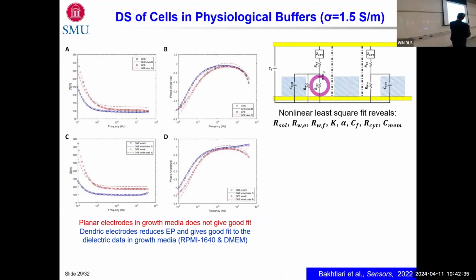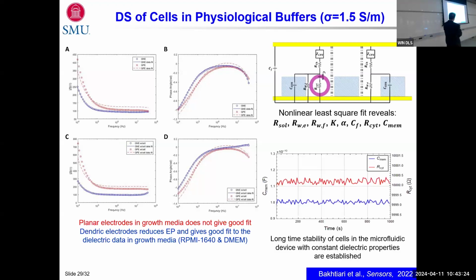So then, by using dendritic structures, we were able to make measurements. And the top figures A and B, one is the impedance magnitude, the other one is the phase angle. The red shows the planar electrodes, and our fits to that, with dashed lines, are terrible. However, the blue dots and blue solid lines are obtained with the nanostructured electrodes. And as you can see, the data matches very nicely. Over here, you can also see that when you have cells in it, you're doing pretty well as well. So this basically opened up dielectric spectroscopy in physiological buffers.